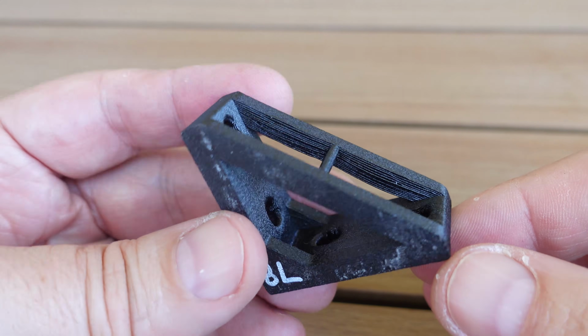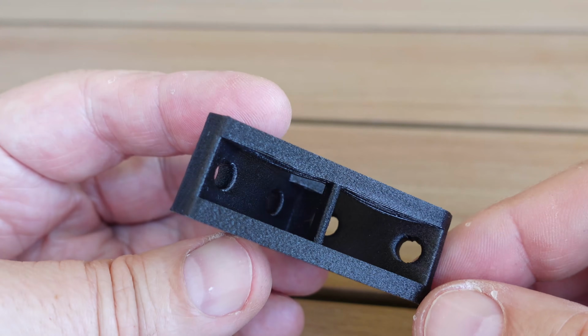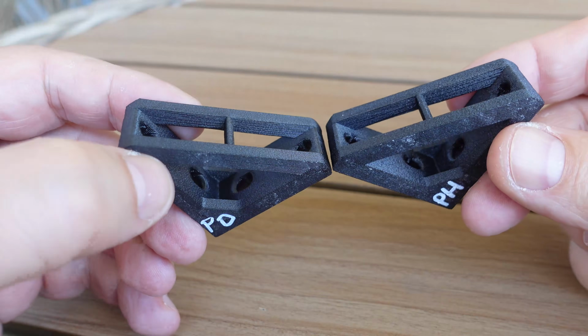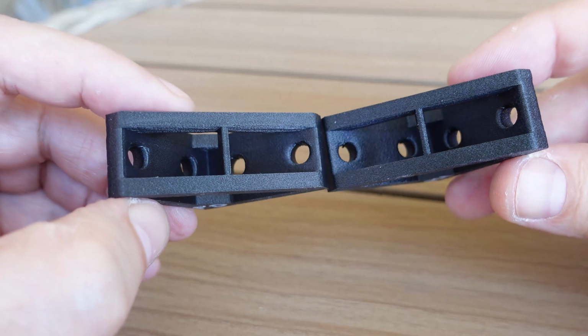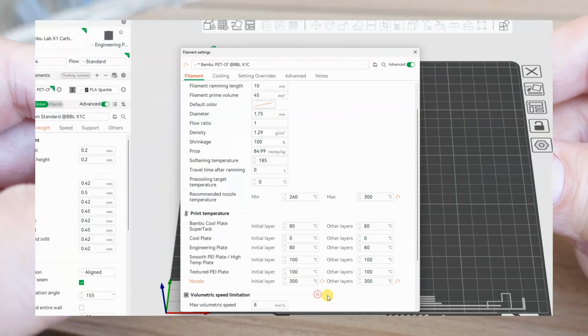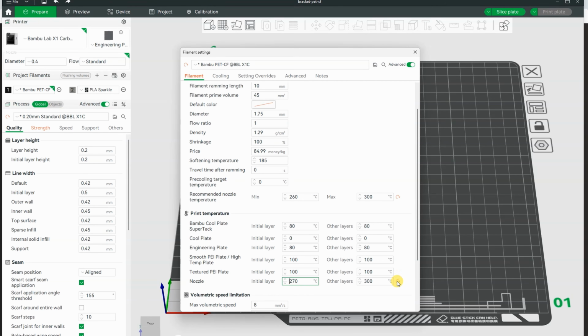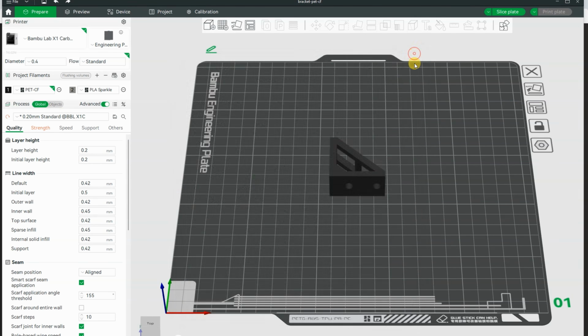Only on this bracket from the BambuLab I noticed that bridging didn't come out nice. In every other case they are perfect. But this is the only filament where the default setting is 270 degrees Celsius, but I printed everything at 300, much higher. So I decided to reprint these test objects from the BambuLab using the default settings.